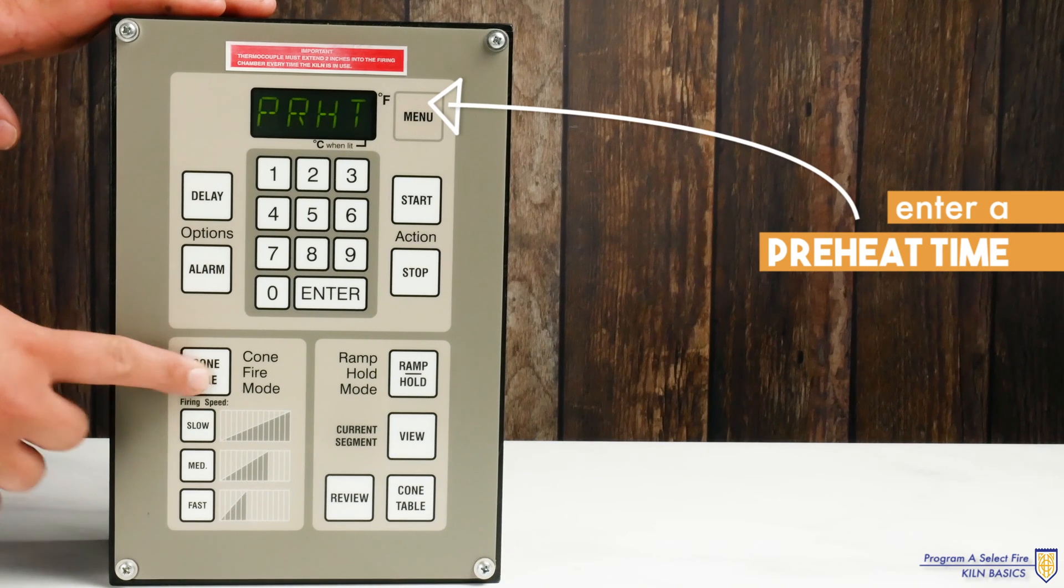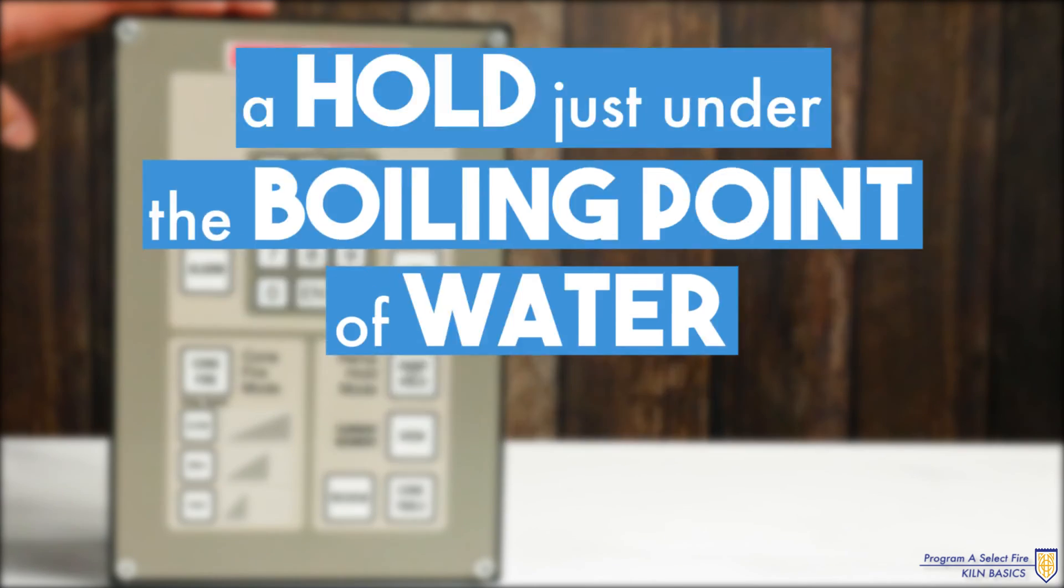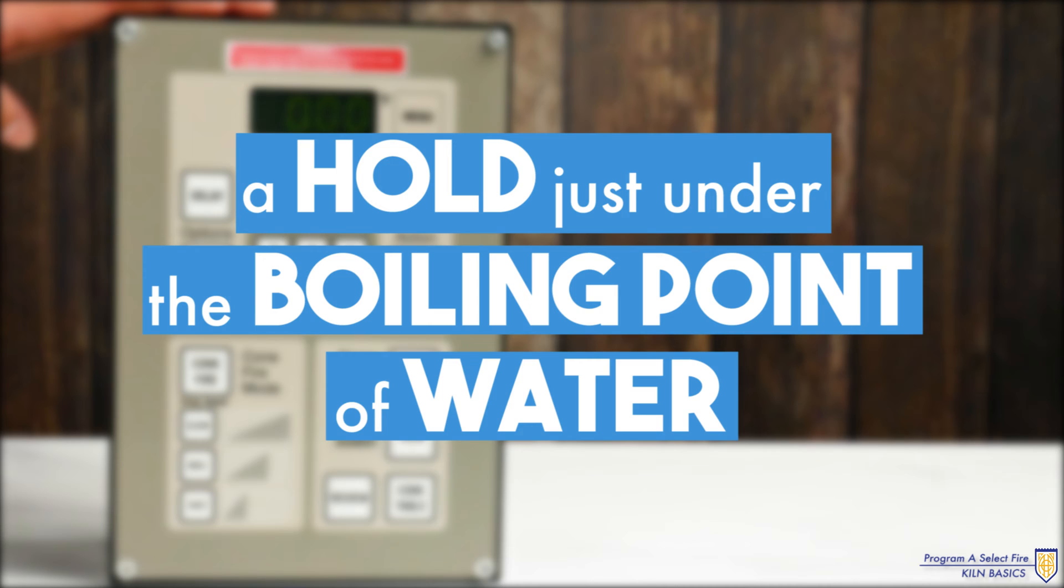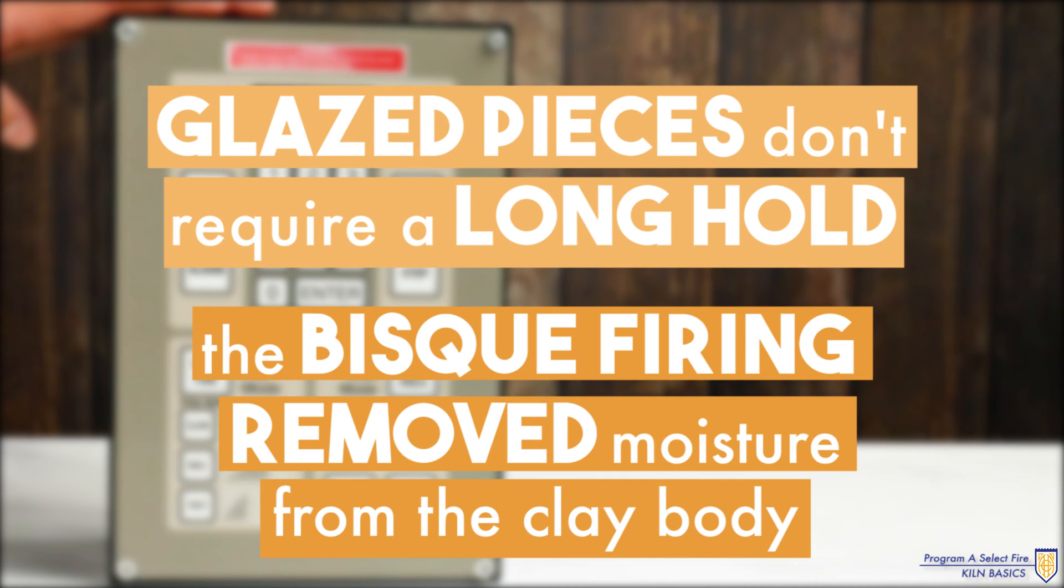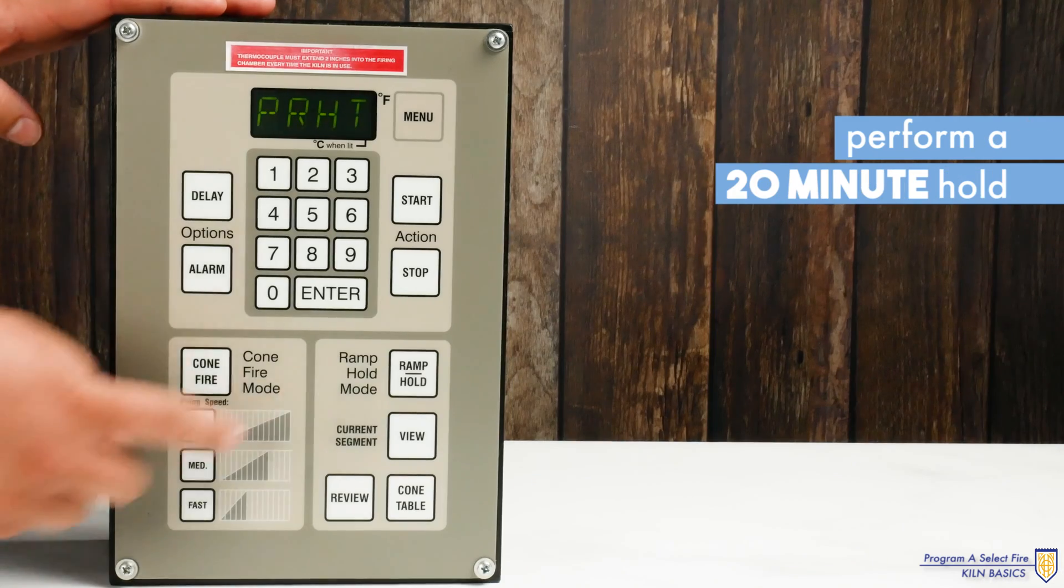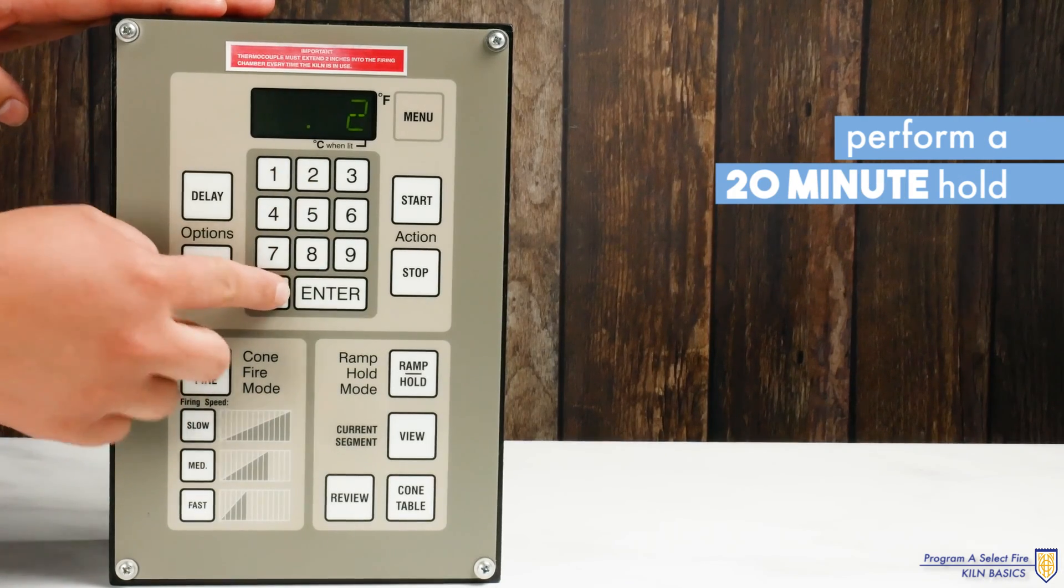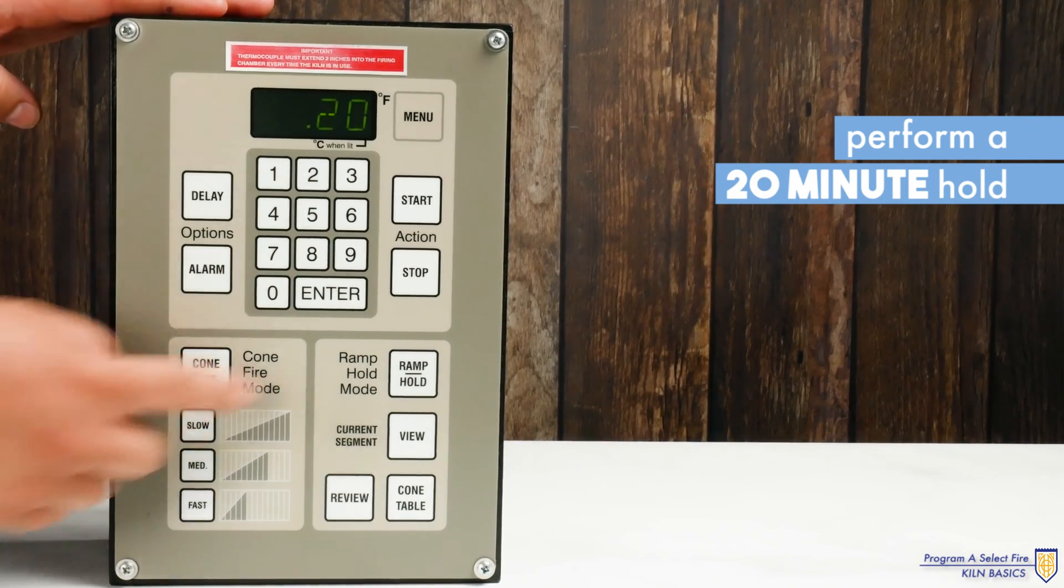It will then prompt you to enter a preheat time. Again this is a hold just under the boiling point of water. Glazed pieces do not require very long hold since the bisque firing already removed the moisture from the clay body. We will perform a 20 minute hold just to remove any added moisture the glazing process may have added.